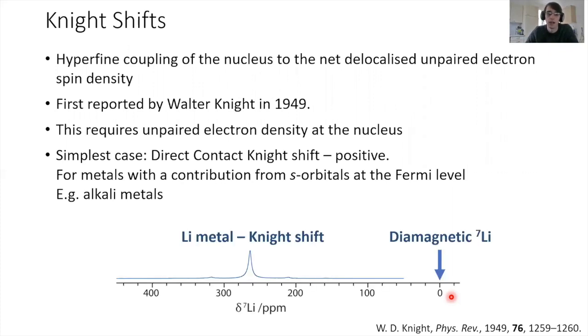So showing that here, the case of lithium metal, the 7Li spectrum, and you may be familiar that in diamagnetic lithium compounds, everything comes within a few ppm of 0, which is quite frustrating if you're trying to assign lithium spectra, but lithium metal comes out here at 270 ppm. And that's because we've got these delocalized unpaired electrons due to this Pauli paramagnetism. In s orbitals, they have a direct Fermi contact shift on our 7Li nuclear spins. Okay, so that's what most people will think about when they think of a Knight shift.